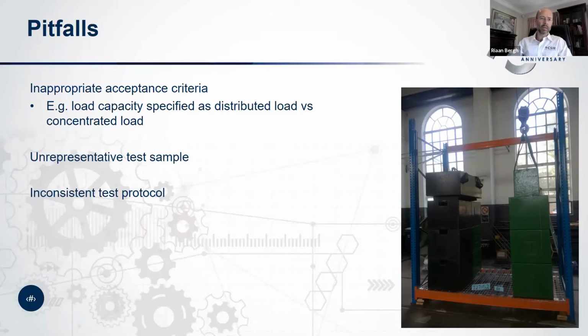And then lastly, two more pitfalls to avoid would be one of an unrepresentative sample. And here I'm reminded of the case of a steel wire rope that failed in service, and a sample of the rope was sent to the laboratory to do a destructive tensile test to confirm the tensile load that would cause the rope to fail. And it was difficult to understand why the failure occurred, because the tensile strength of the rope sample that was sent to the lab was still well above the applied load on the day of the failure.